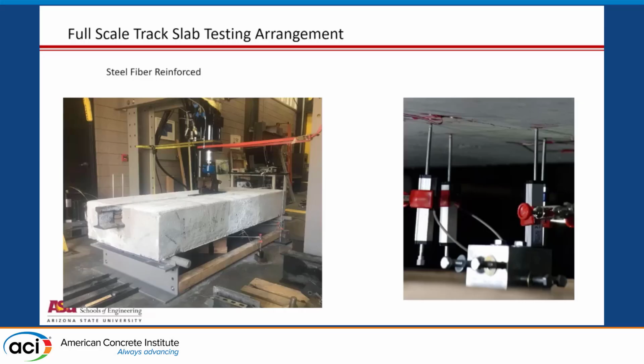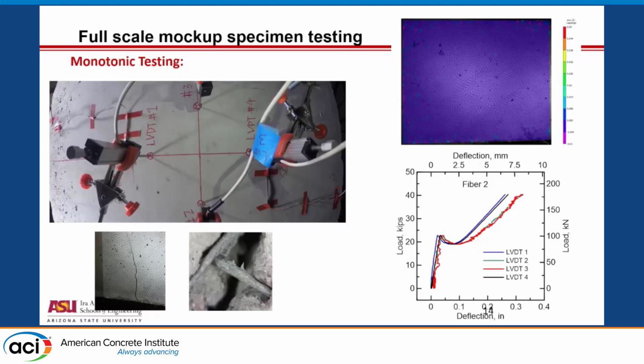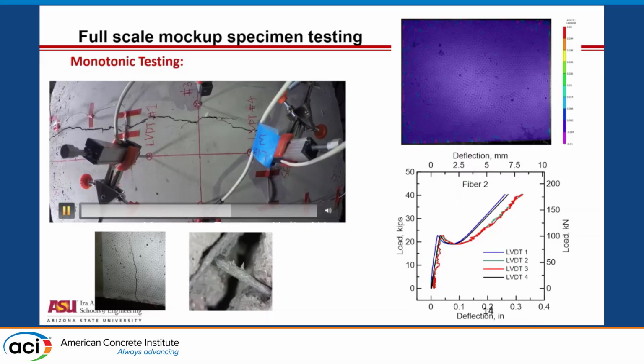There are 2 support lines, and under the beam we had about 16 transducers that measured the entire deflection of the section. Then we went through running the test, and here are some tests. So let me just see if I can start this video. As the load is applied, we can see that a crack forms, the crack opens, and this is the initial reinforced concrete section that very clearly shows the formation of a single crack that dominates.